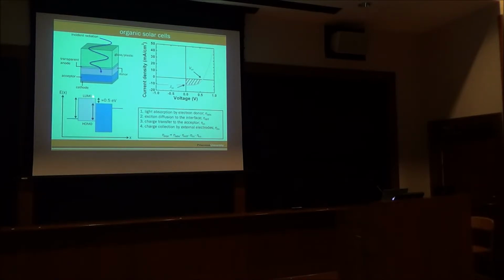Then finally, there's this loss here, this LUMO-LUMO difference. This, remember, is the driving force for us to split the exciton. And this needs to be about 0.5.